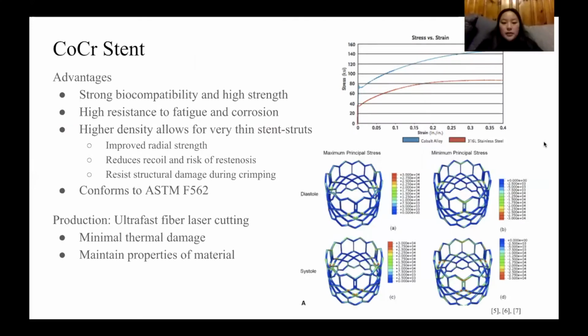Medtronic performed several tests comparing stainless steel and cobalt alloy stents and found that cobalt alloy stents maintained a strong biocompatibility but have a higher ultimate tensile strength, as seen from the stress strain curve to the right, showing that they can withstand the stresses placed on the stents during blood flow. Medtronic also found that cobalt chromium has a higher density than stainless steel, which allows for very thin stent struts while maintaining strength. Thin stent struts provide many advantages, including radial strength, reduced risk of recoil and restenosis, and resistance to structural damage during crimping. The cobalt chromium stent proposed by Medtronic was also found to conform to the ASTM F562 standards, which are for a cobalt alloy surgical implant.